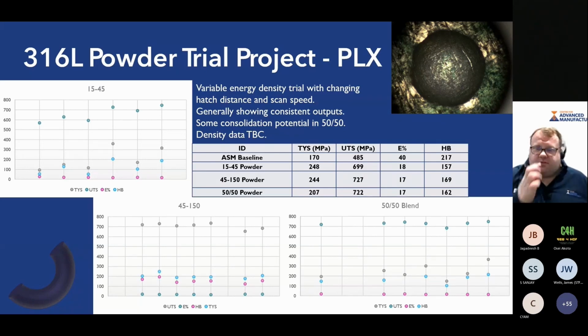Had a couple of gaps because of some issues in terms of how flat the coupons were in the end. I think we maybe were a bit overzealous on the polishing, and we didn't have the squareness that we'd need to get those data points. But generally speaking, there seems to be some performance consistency between our 15 to 45 trial and our 50-50 and our 45-150.